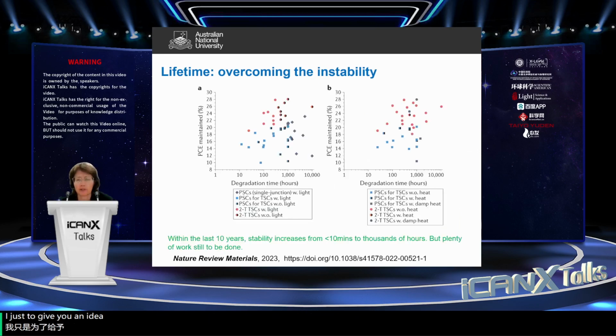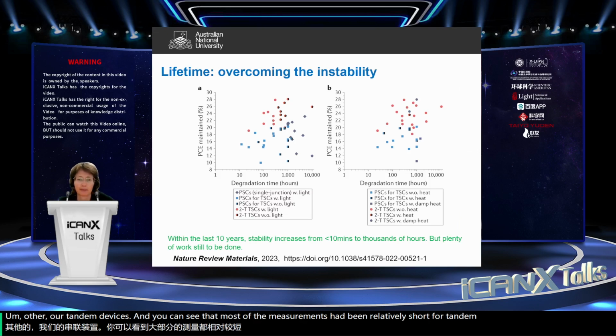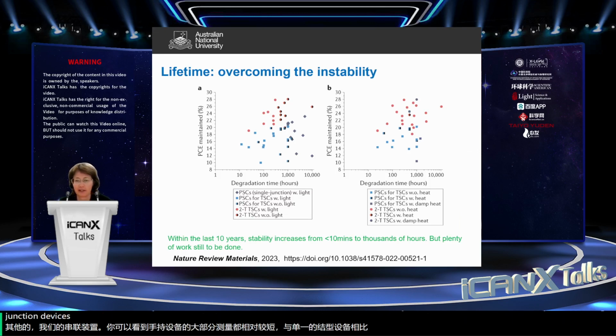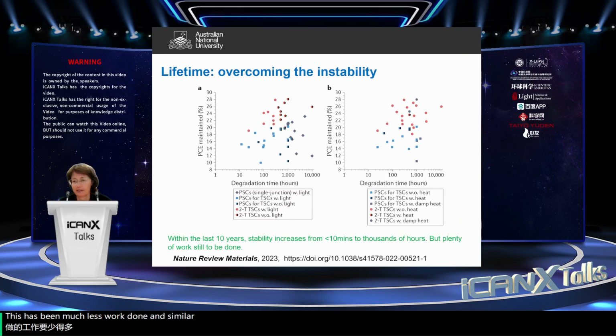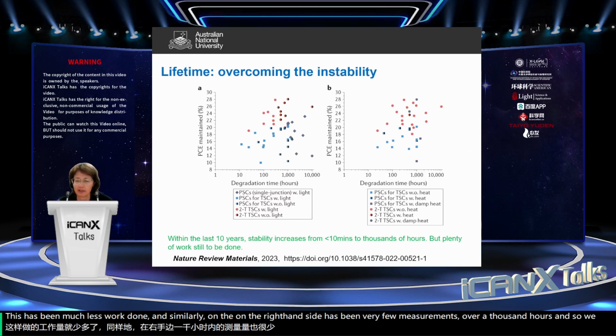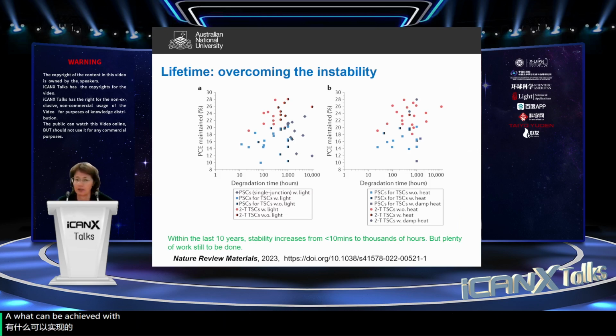Just to give you an idea of how much needs to be done, there's much less work that's been done on perovskite silicon tandems than on single junction perovskites. So you can see on the left-hand graph here, the red dots are the tandem devices, and you can see that most of the measurements have been relatively short for tandem devices compared with single junction devices. There's just been much less work done. And similarly, on the right-hand side, there have been very few measurements over 1,000 hours. And so we just don't know what can be achieved with perovskite tandems. So there's very much work to be done.